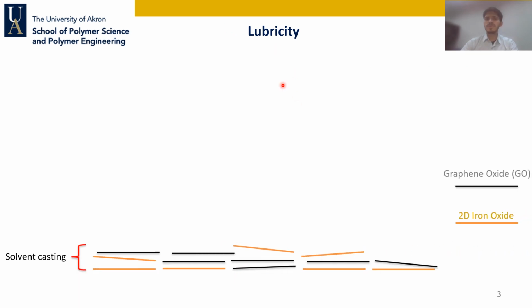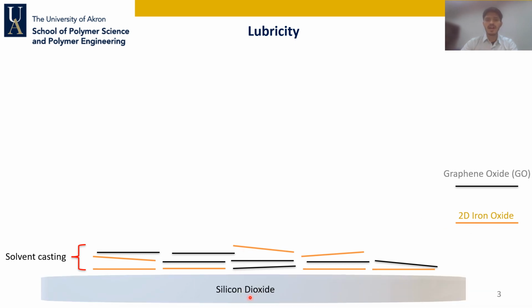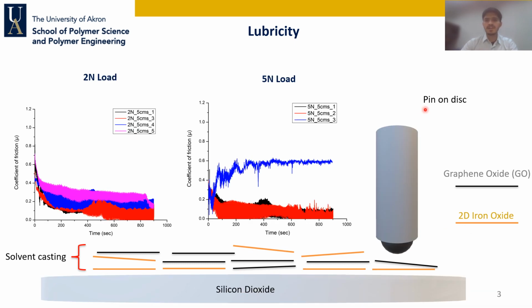So we started the lubricity study by solvent casting the graphene oxide and 2D iron oxide on our silicon dioxide substrate, and we did the pin-on-disc measurements at 2 Newton and 5 Newton loads. What we observed in common was that both of them showed coefficient of friction values close to 0.2 and even less than 0.1 at higher loads.